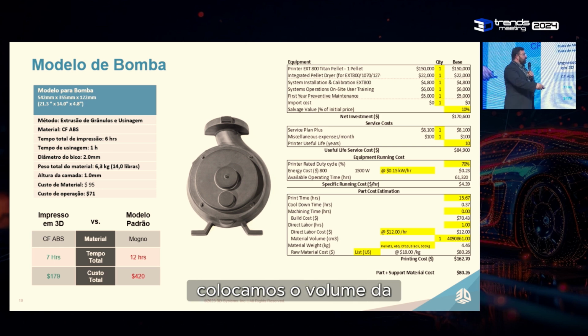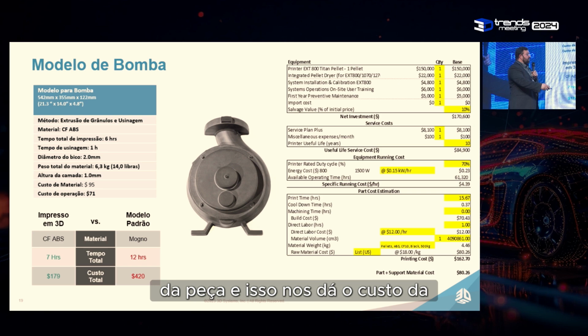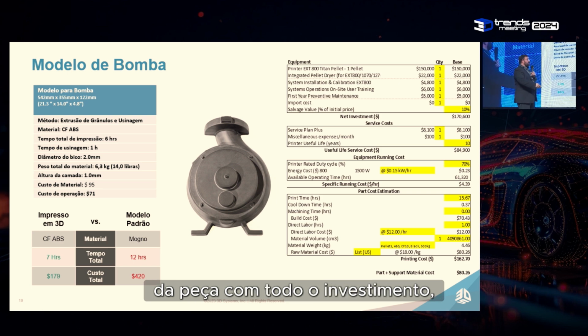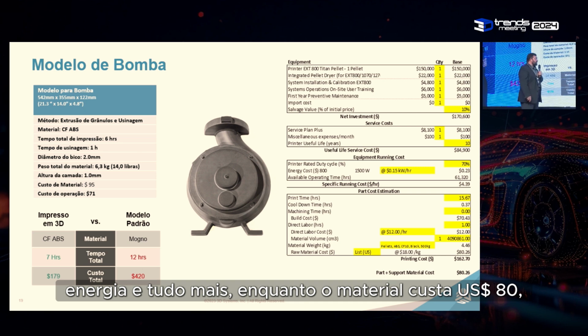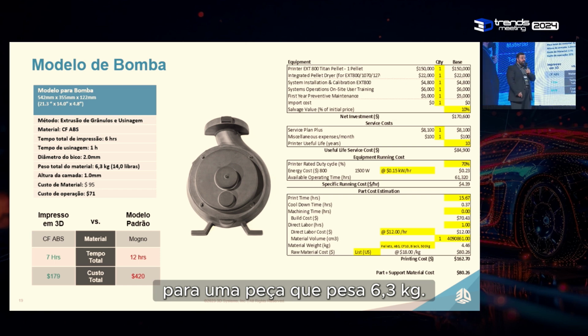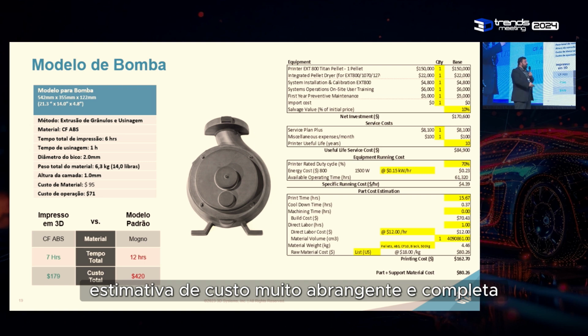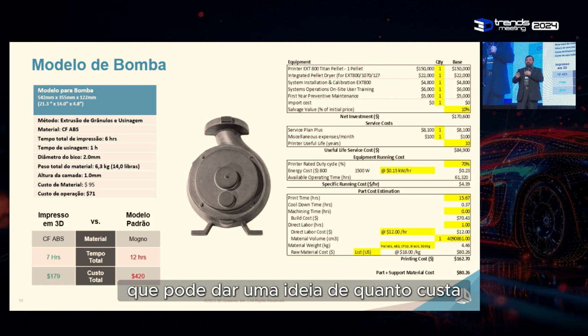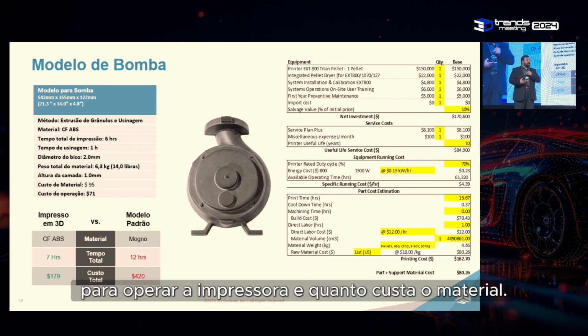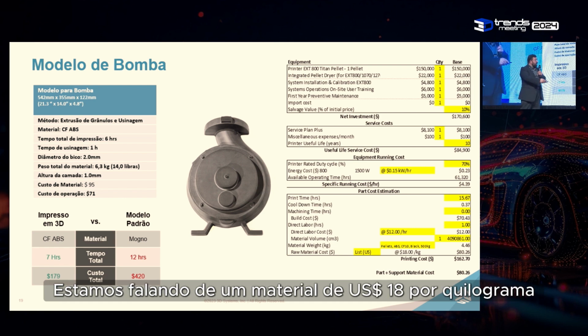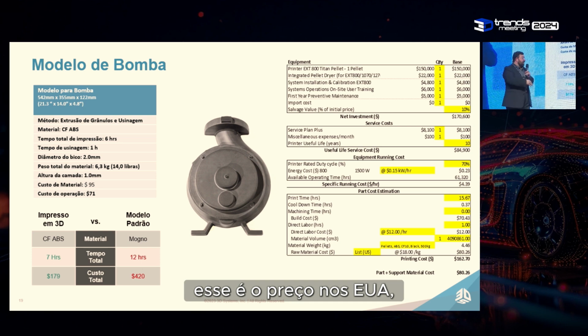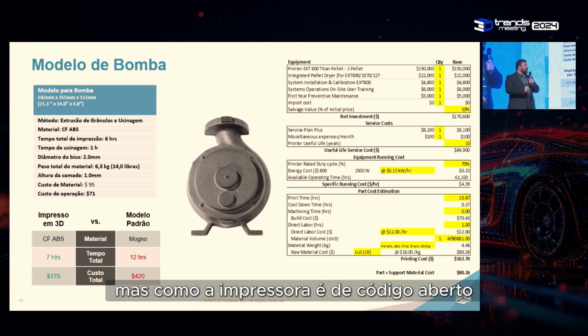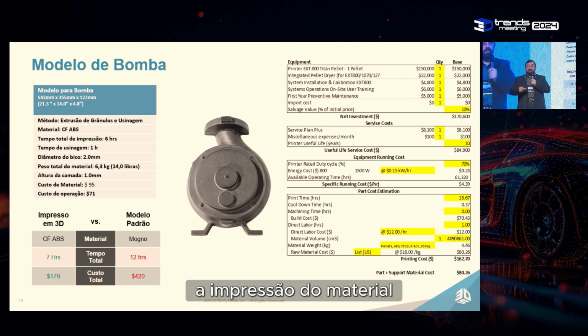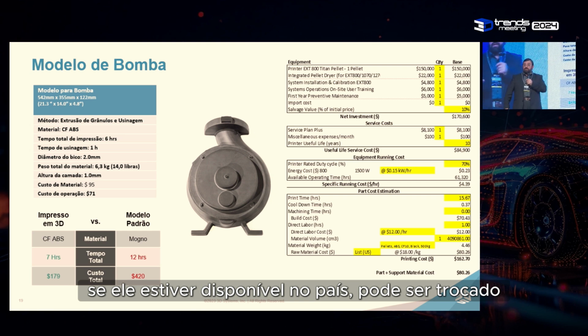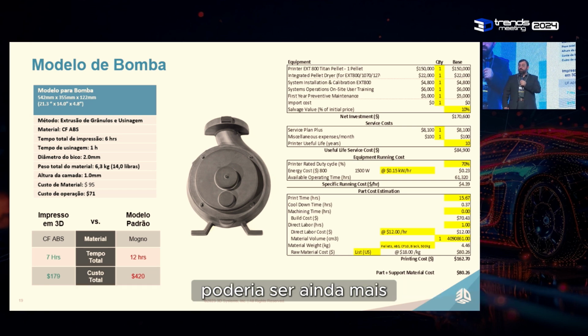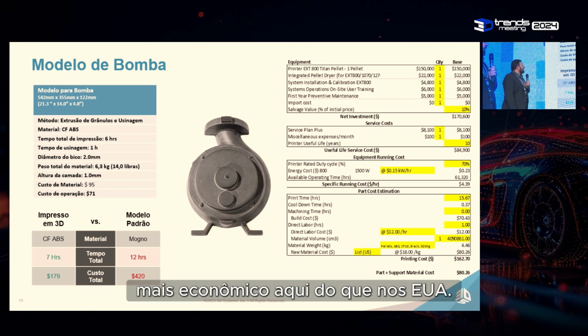We put in the volume of the part, and this gives us the cost of the part with all the investment, energy, and everything, while the material is $80 for a part that weighs 6.3 kilograms. This is a very comprehensive and complete cost estimation that can give an idea of how much it costs to operate the printer and how much the material costs. We are talking about a material at $18 per kilogram. This is priced in the United States, but because the printer is open source, the material, if it's available in the country, can be changed for a local source with no problem, and could even be more cost effective than in the US.